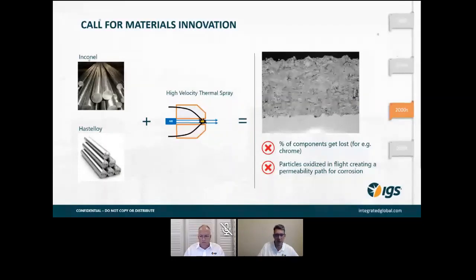It's heating these materials up very quickly. It's spraying the material through the atmosphere, atomizing it in the spray gun, but then those molten particles travel to the surface that they're going to deposit on through the atmosphere. Although that flight path is very quick and very short in terms of time, there's opportunity for the molten particles to react with oxygen, principally oxygen, in the atmosphere.